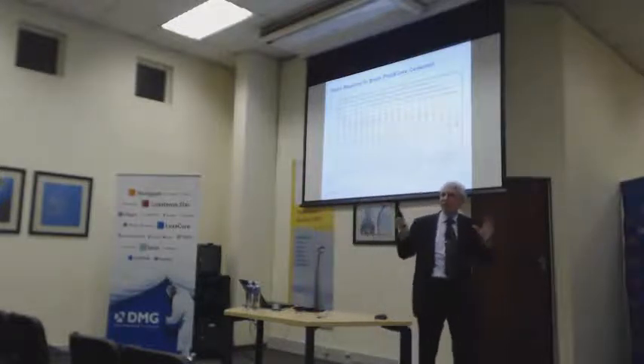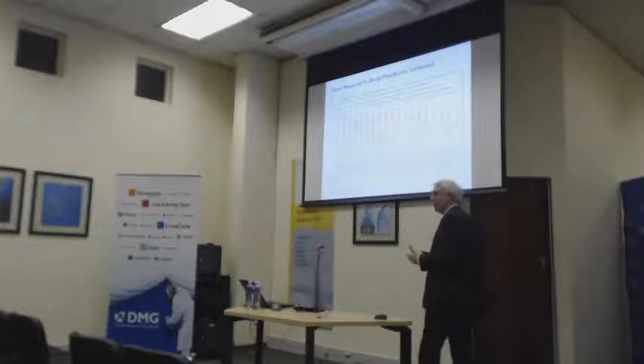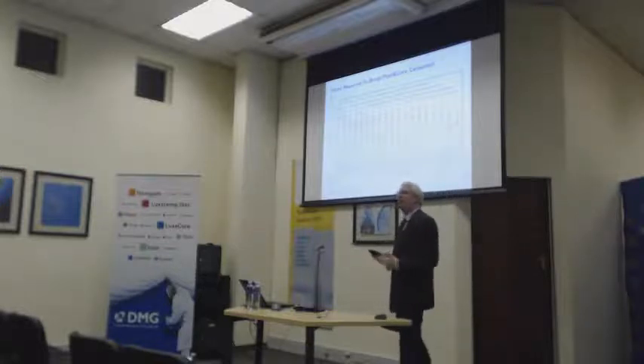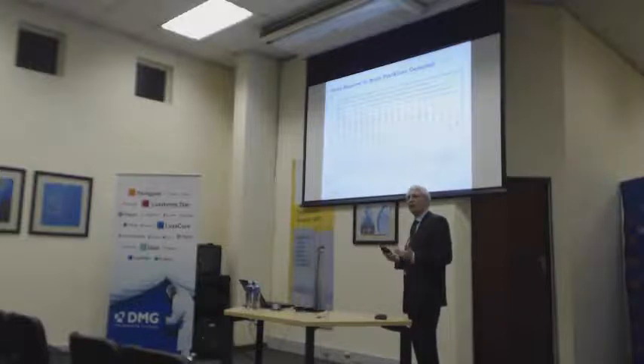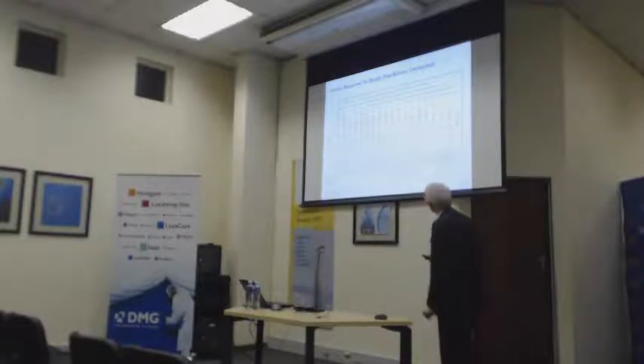So everything in this group is statistically the same. It doesn't matter whether you use a metal post, a glass fiber post, a ceramic post, or a carbon fiber post. They all perform very, very well. They withstand very high loads before they fracture.